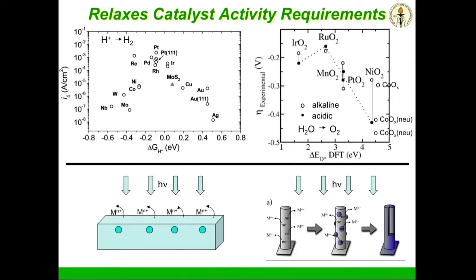One is that we would rather use earth-abundant catalysts. This is the so-called volcano curve. It shows you the hydrogen evolution catalyst activity for various metals on a log scale. And of course, platinum is the best. And of course, nature's not kind to us, because platinum being the best is also one of the least abundant elements on Earth. On the other hand, unlike a fuel cell that runs at an amp per centimeter squared, the solar photon flux is 100-fold less. It only produces 10 milliamps per centimeter squared.